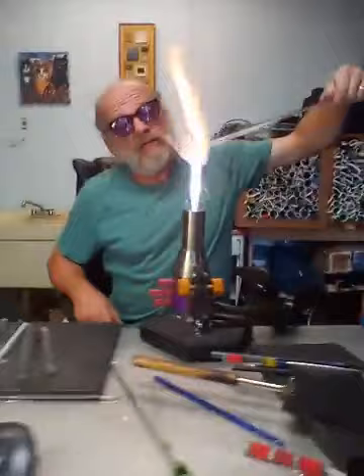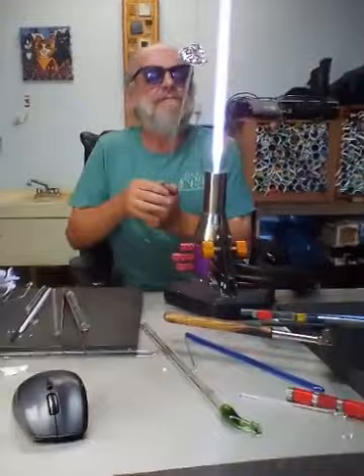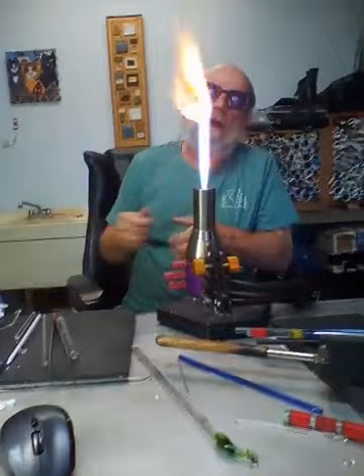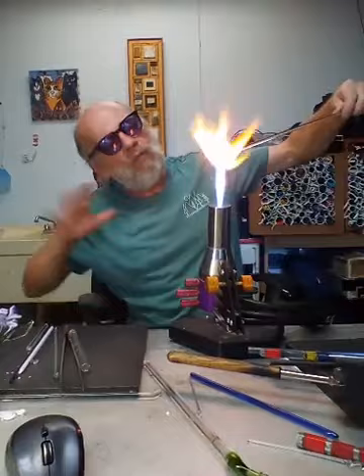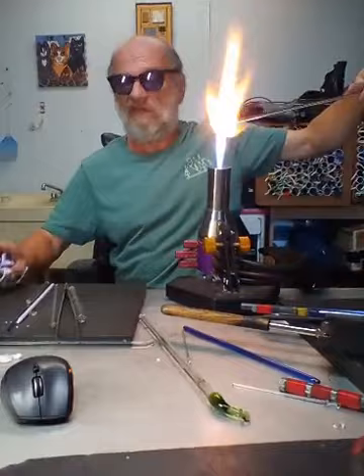This is a base I made just previous to the demonstration. I'm doing this a little bit out of sequence and I might lose this base. All I'm trying to do right now is just keep the base hot — I don't want it to crack. It's right around 1,000 degrees, and once it gets up to around 1,200 degrees it can start deforming. Typically I don't do this in this sequence, but I wanted to make it a little bit more interesting and not take forever.